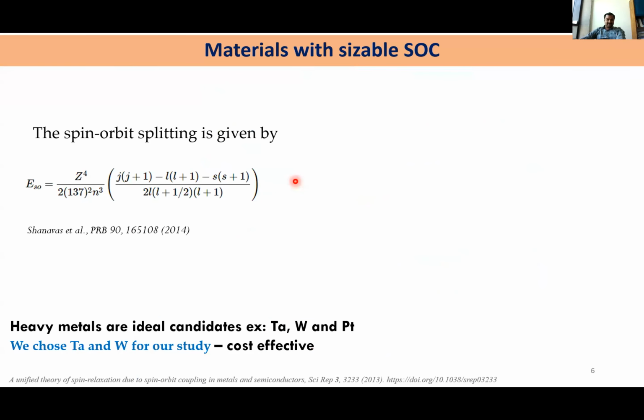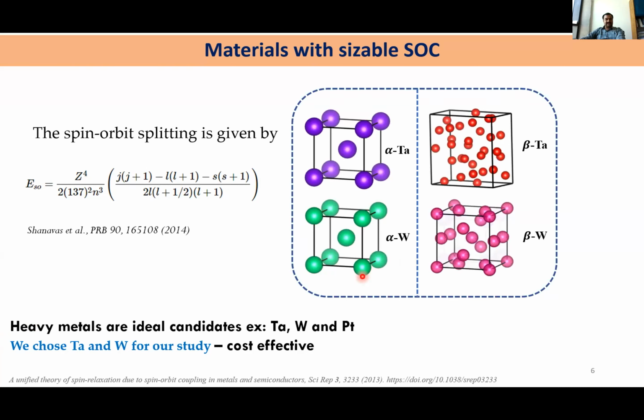So what are the materials with sizable SOC? What kind of non-magnetic materials should I use? That depends on the spin orbit coupling splitting energy, which is directly proportional to Z to the power of 4. So obviously heavy metals are the ideal candidates, and as Professor Subhankar mentioned, platinum is not cost effective. So in our study we chose both tantalum and tungsten, and both can have two crystalline phases. Tantalum can be in the BCC phase, or it can be in a metastable BCT, body centered tetragonal phase. Similarly, tungsten can be in BCC or it can be in the A15 structure.